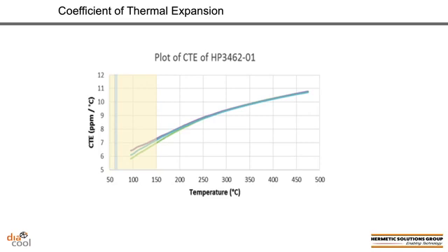So when you take this Diacool metal matrix composite material and test it for CTE, you get these kinds of results. You can see in this chart where I've measured this material over a broad range of temperature from essentially room temperature up to 475 degrees C. And I've looked at the coefficient of thermal expansion of various lots of this material. The tan bar that you see here is essentially just put there to represent the kind of operating temperature of most device technologies today. And you can see in all cases that this material has a very friendly coefficient of thermal expansion that sits right around that 6 to 7 ppm kind of range.